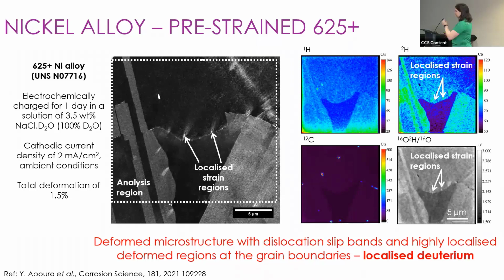And it's a little bit difficult to see on the projector, but you can actually see deuterium is now segregating to those localized strain regions as well. So once we've got a deformed microstructure and we've got dislocation slip bands, we start to see localized deuterium at these particular grain boundaries. So then what we did is we increased the complexity again, and we actually looked at